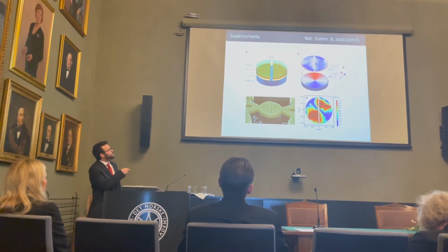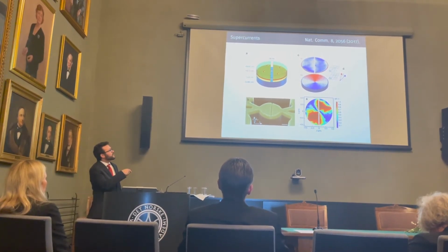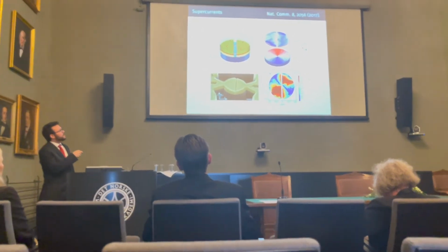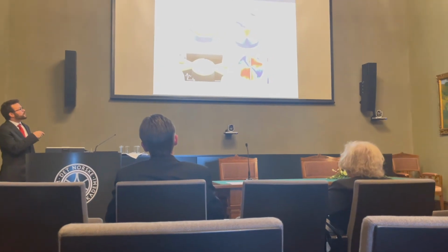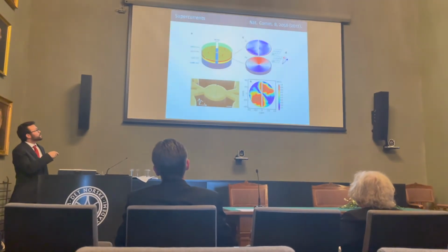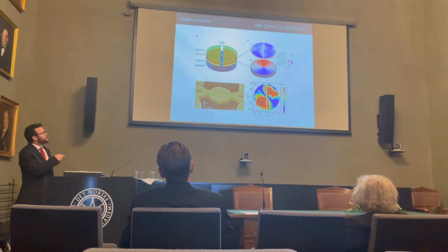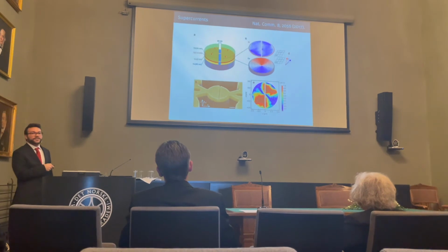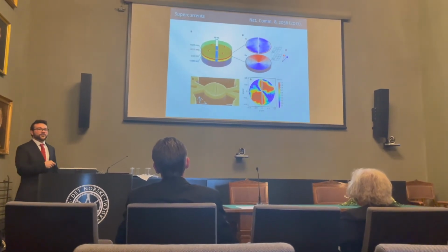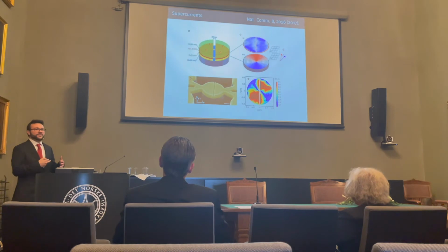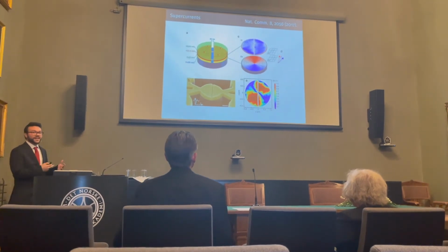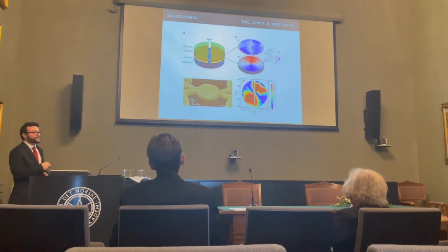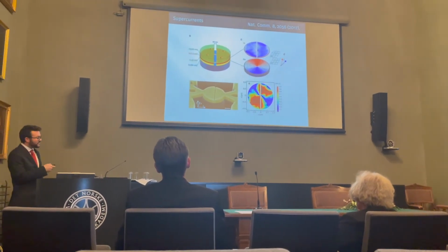And then they took an ion beam and they cut a trench through the device here. And what this meant was that the only way electrons in this half of the superconductor could end up in this half of the superconductor would be if the electricity flowed down into this magnetic vortex and moves a bit over here and comes back up on the other side. And this means that you can learn a lot about how superconductivity interfaces with magnetism in this kind of device by basically studying the current flowing down here and up here between the two halves of the superconductor.